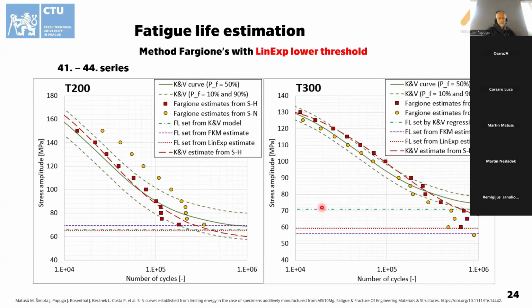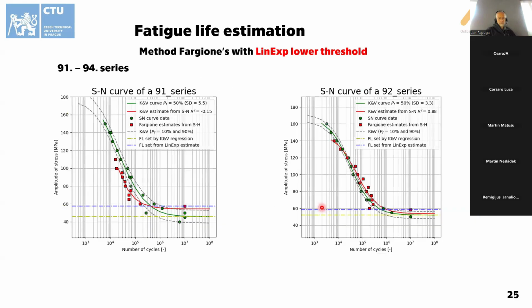All of these SN curves were set using only 3 samples. So 3 samples for the self-heating step test, out of which we did the LinExp approach, finding the fatigue limit, and also did the fatigue life prediction by Fagione's approach. This was also done for the 91 to 94 series with variable success. The 91 series did not work that well, in my opinion. For the 92 series, we have a really tight spread. Yeah, this is unique for fatigue, I guess.